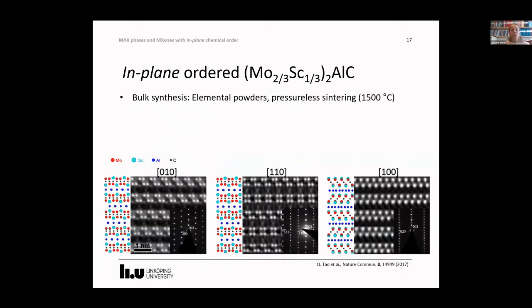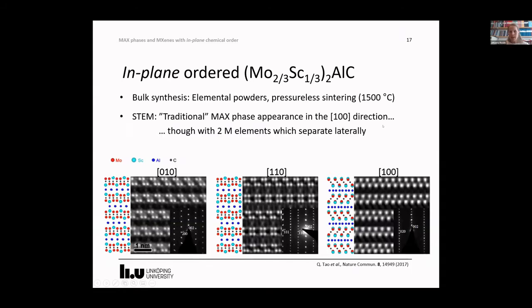The first MAX phase that we discovered that had this in-plane chemical order was molyscandium aluminium carbide. It was actually discovered simultaneously when we grew thin films and when we did bulk synthesis. For the bulk synthesis, we mixed elemental powders and used pressureless sintering. When we looked in the STEM, we found a material which looked like a traditional MAX phase in the 100 direction, but which had two M elements which separated laterally in the other orientations. And from the STEM and from the electron diffraction, we could conclude that we had a monoclinic phase as opposed to the hexagonal MAX phase.